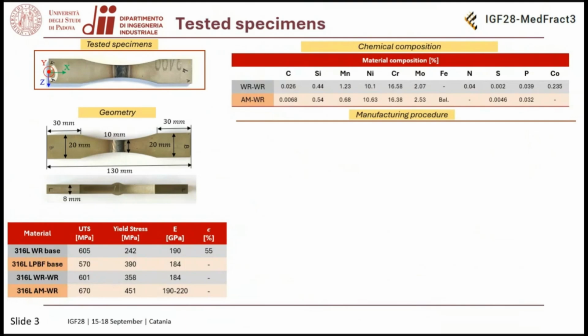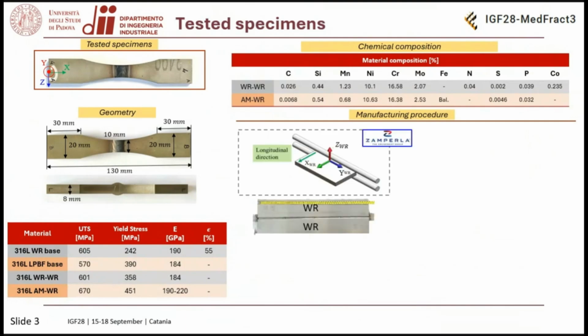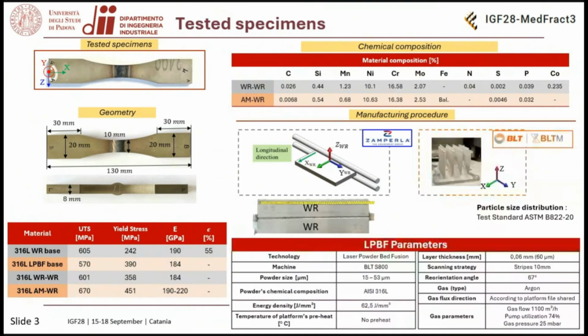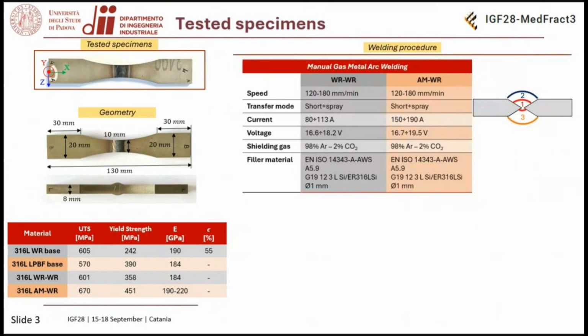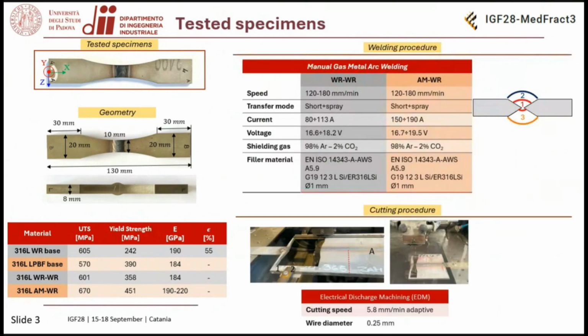We also monitor the manufacturing process, and so talking about traditionally manufactured welded joints, they are produced from hot rolled plate. In the case of joints with an AM part, we have the plate with this building direction, and this is the building direction that we can find here in the specimen. Then we weld the two plates with three passes, and finally cut them through EDM, obtaining these final shapes.